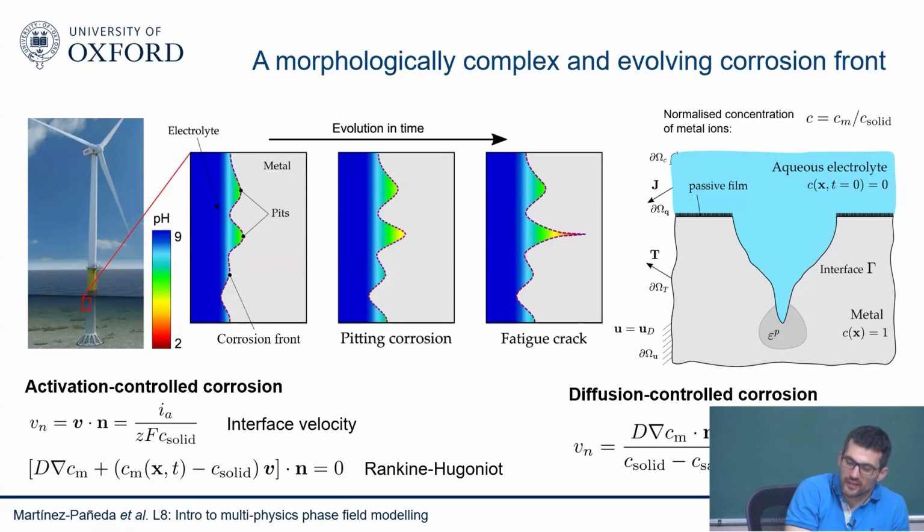It will come. Because this is an important coupling with mechanics, right? What do we do when we have corrosion problems? We use corrosion-resistant materials that develop a passivation layer that prevents corrosion from happening. Then mechanics interplays with corrosion by rupturing that passivation layer, and then the passivation layer forms again. So there's an interplay between mechanics and corrosion. That will come later as well.